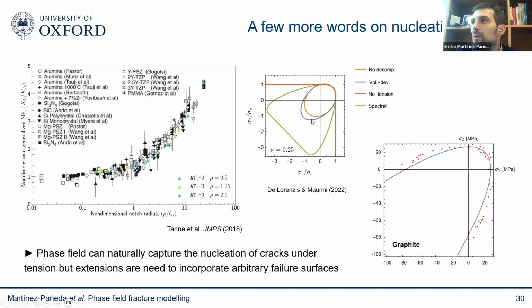So there's a lot of people who have come up with ways of doing this. Sometimes they're called strain energy splits. So what they do is, instead of taking the full strain energy density as the driving force for fracture, so all the energy stored, they divide that into an active part and an inactive part, or sometimes called a tensile part and a compressive part, and then they drive the fracture only through the active part. And this is what you see here with the volumetric-deviatoric split. This is the failure surface that you get.